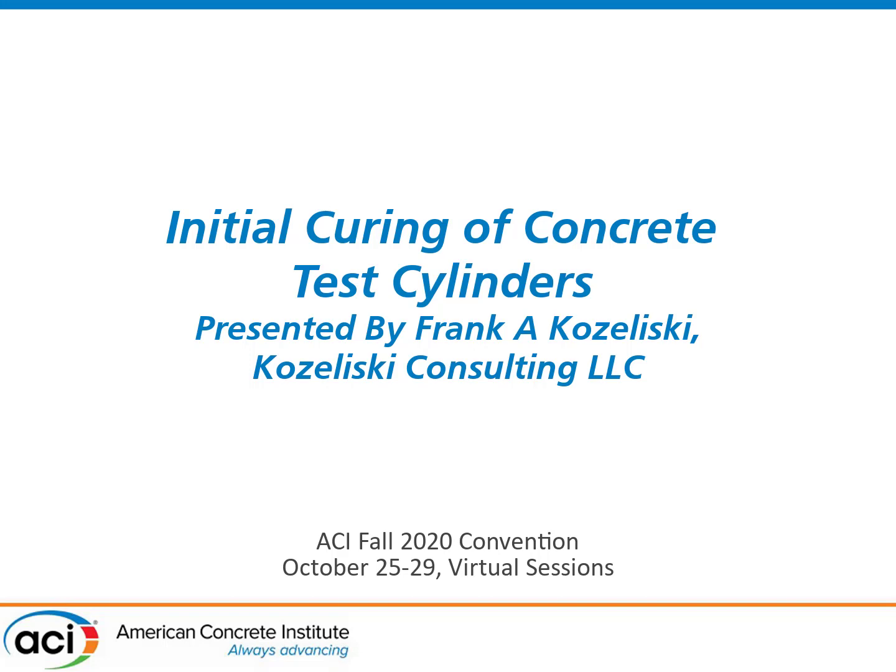Now, the initial curing, as we look at it on C31, I think is the most abused procedure when it comes to testing concrete. People leave the cylinders outside. They don't really take care of them. Colorado has set up a study where they're going to monitor these abused test cylinders. Most contractors and ready-mix people have indicated that 30% of the time, there's a problem on initial curing. It's not being done properly by others. So this is a major problem when it comes to ready-mix producers. Since I was a ready-mix producer, and now I'm back with my old company, trying to provide some of my input into helping them.